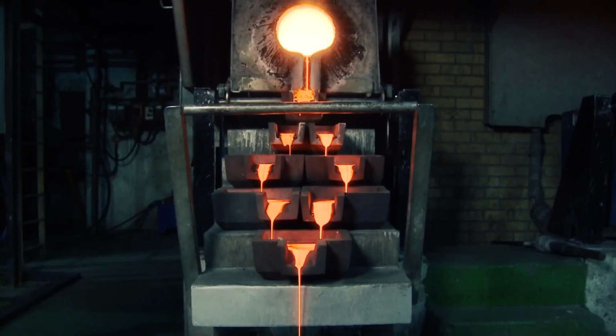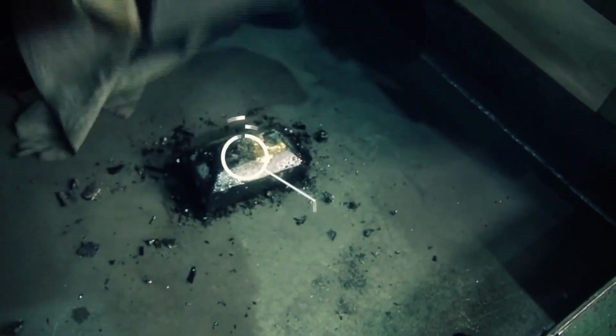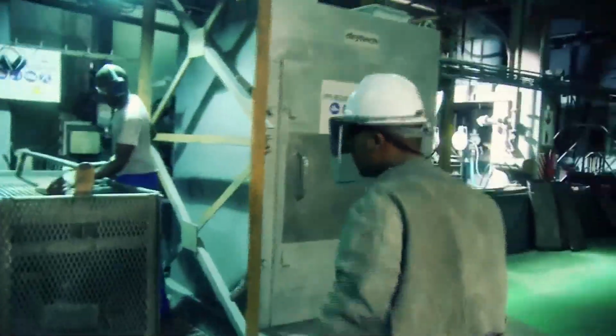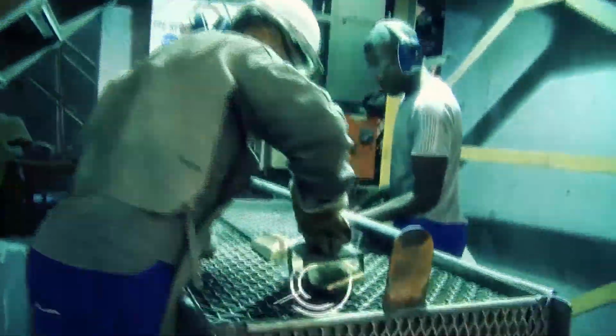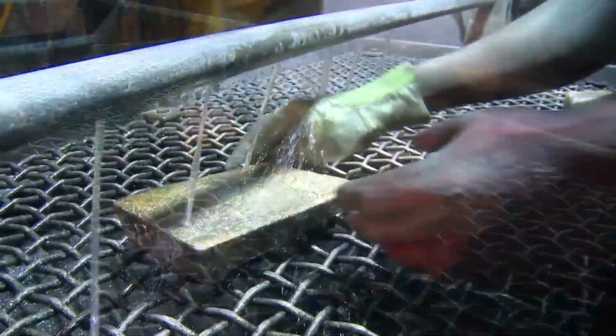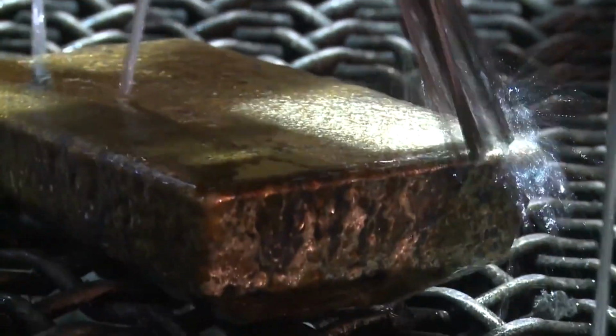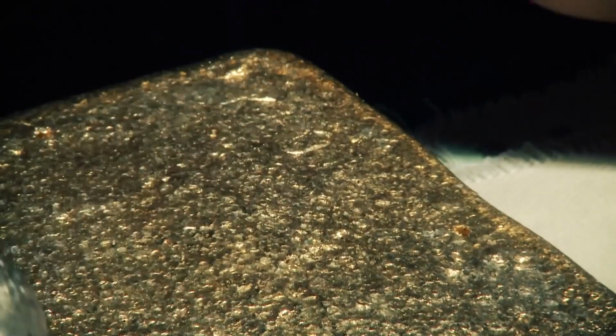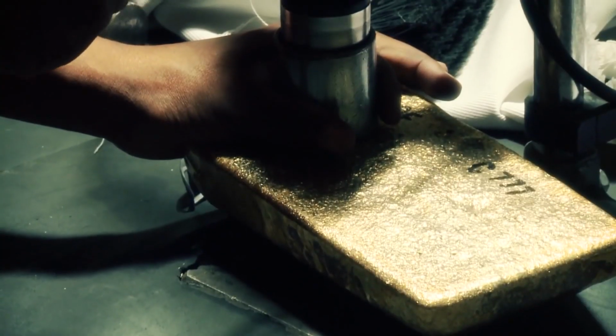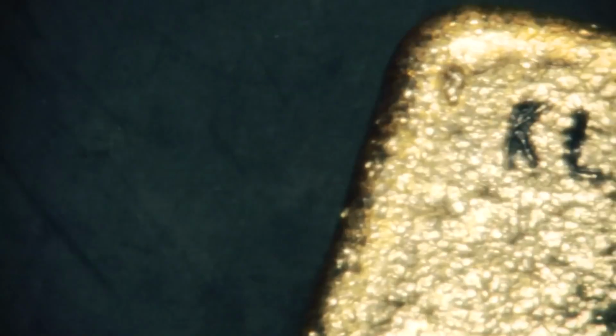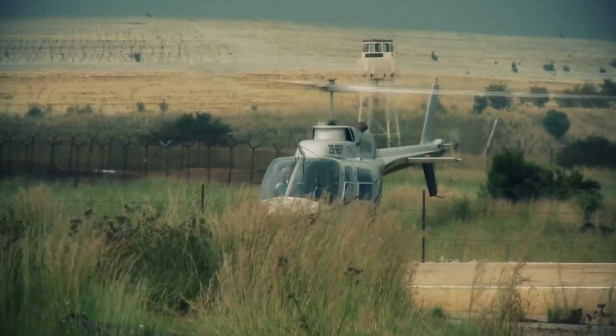The flux is a mixture of several chemical reagents such as borax, silica, sodium nitrate, sodium carbonate, and fluorspar. Borax is a white crystalline mineral used in glass and ceramic enamel mixes. In a smelting process, borax helps to reduce the melting point of the charge and capture metallic oxides. The addition of the reagent must be controlled, otherwise the slag will be extremely hard and non-homogeneous. Another negative effect is that it avoids the separation of phases in the molten charge.